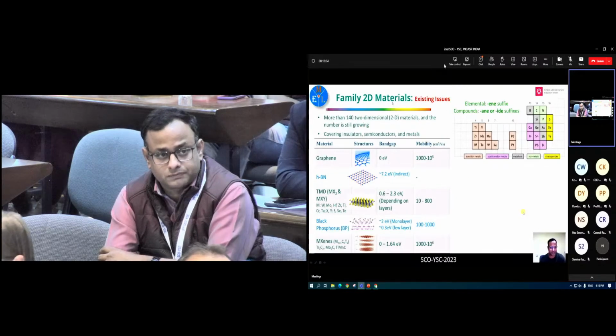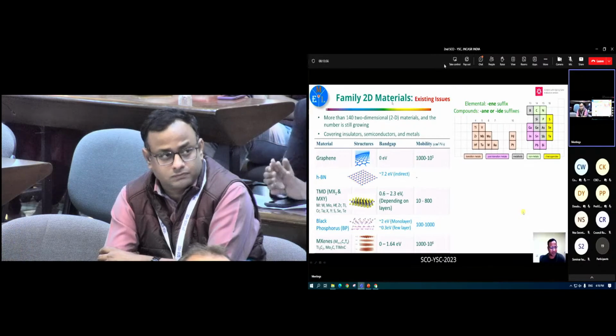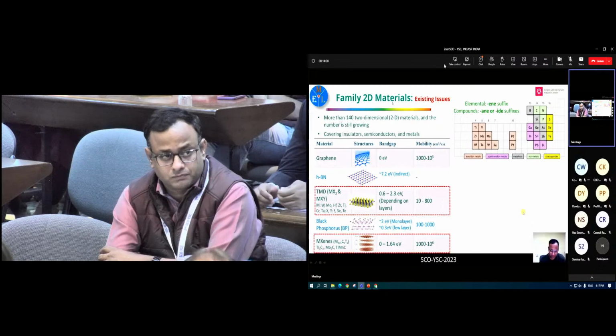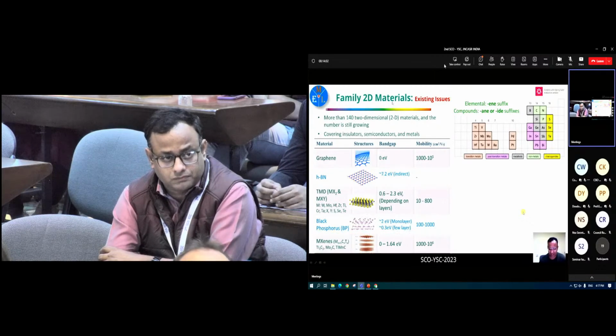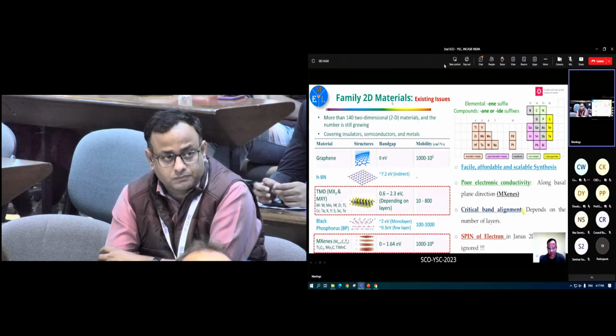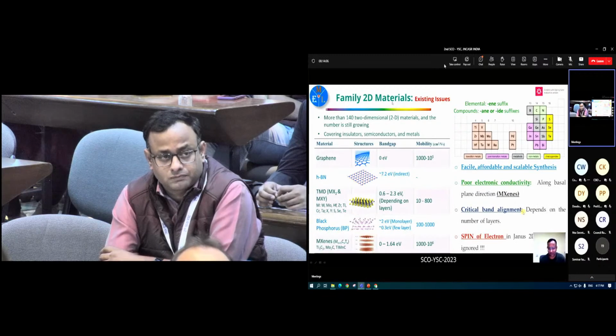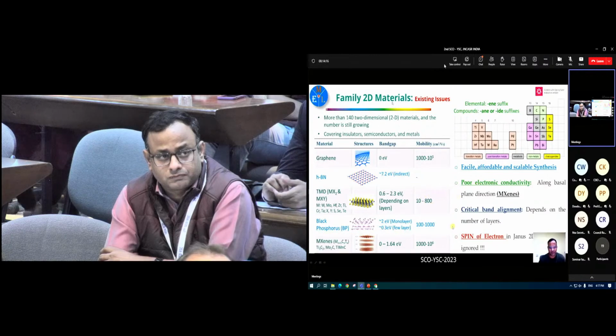So if I tell you about the 2D materials, there are more than 140 2D materials, but there are a lot of issues as far as fundamentals are concerned. Some of the issues which we can address are facile and affordable synthesis of these 2D materials, and electronic conductivity, because if I see here, this chalcogenide has a very low mobility. So that is where, when you mix it with MXenes, we could address this electronic conductivity.